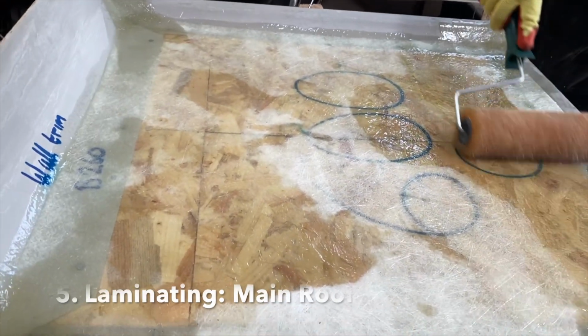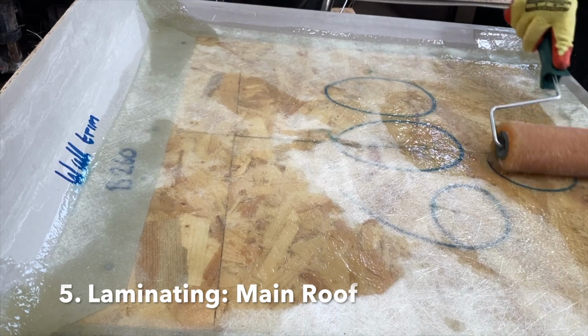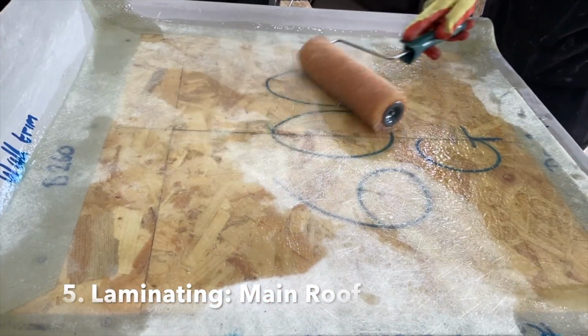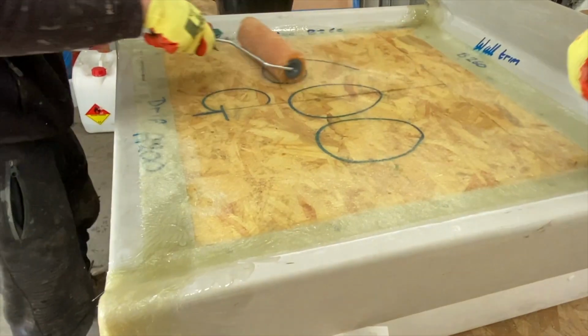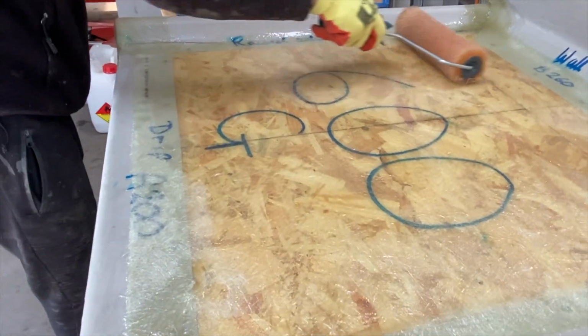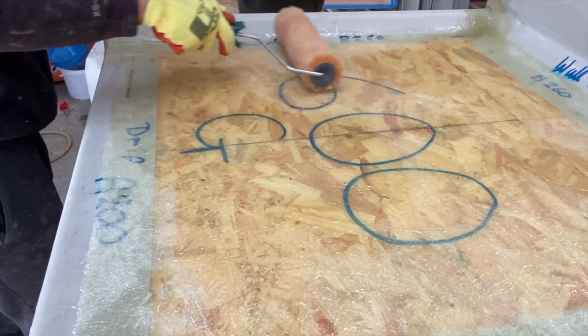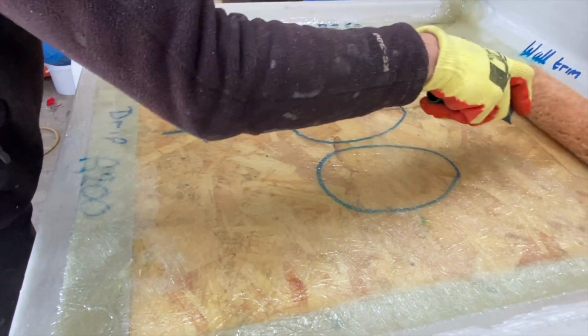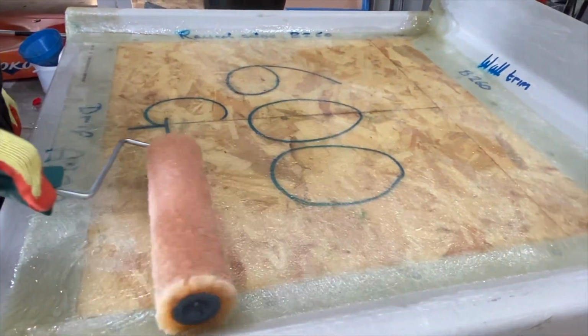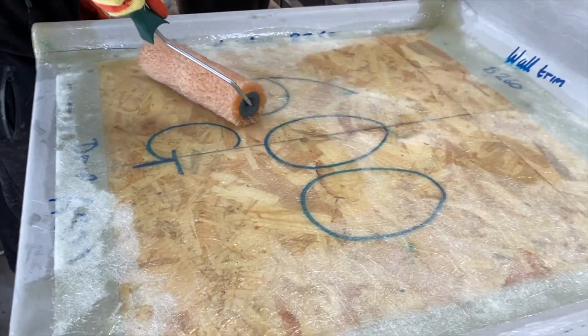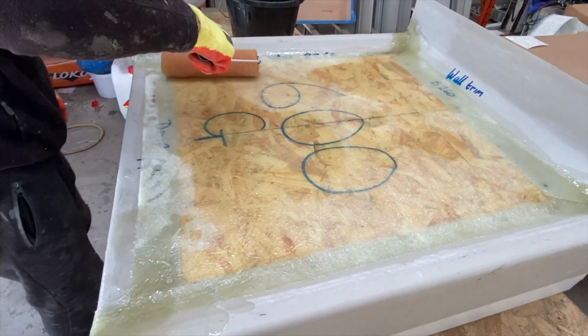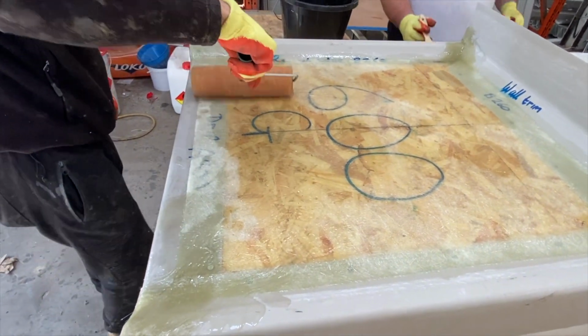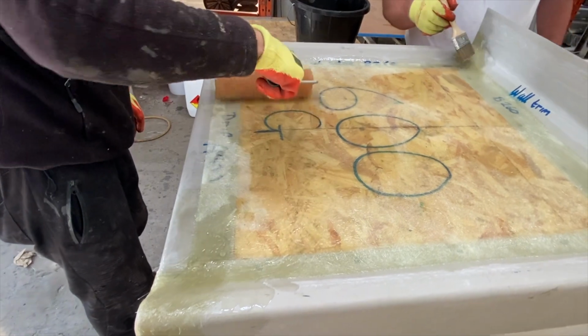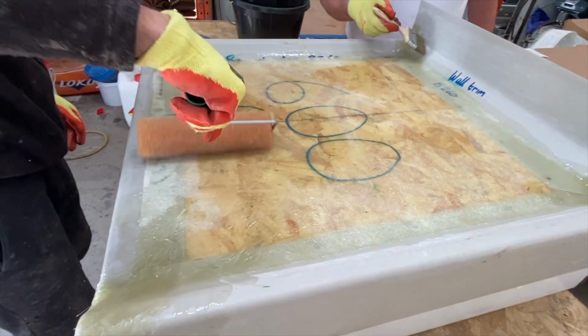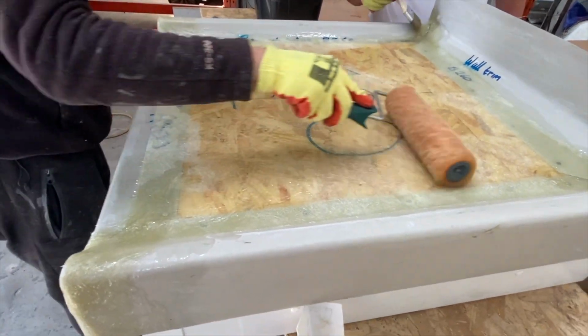When it comes to laminating the main decking part of the flat roof, it's a good idea to place the sheets over the areas you intend to work on and then get adequate workable amounts of polyester resin that's been catalyzed and use a roller to apply the resin to the matting. As you can see, multiple cycles are being applied with the roller across the matting. The aim is to saturate the matting itself in the polyester resin.